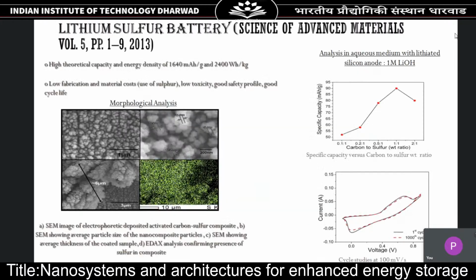Coming to the lithium ion chemistry, one of the devices we studied earlier was the lithium sulfur battery. The lithium sulfur battery was very attractive because it has very high theoretical capacity and energy density. The capacity can be as high as 1640 milliampere hours per gram, and energy density can be as high as 2400 watt hours per kg. The fabrication cost is quite low because sulfur is used, toxicity is less, and it has a good safety profile and cycle life.